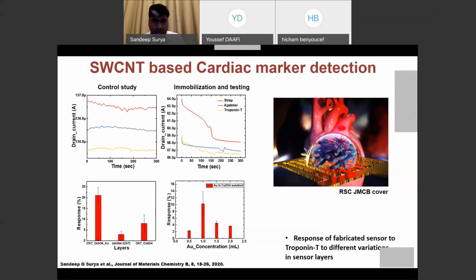sensitive towards troponin T. And among the three different types of receptor layers that we have deposited, carbon nanotubes had very minimal change as compared to the cobalt oxide nanorods. And what we have seen is that gold loaded cobalt oxide nanorods had really very good sensitivity as compared to the cobalt oxide nanorods alone.